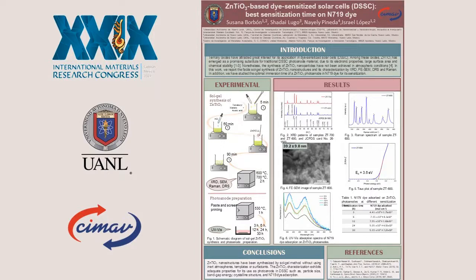In conclusion, we have synthesized monocrystalline nanostructures of zinc titanate with suitable optoelectronic properties for its application as photoanode in the DSSC. In addition, we have demonstrated that the optimal sensitization time for N719 dye is 24 hours, endowing a dye loading in the order of 10^-5 mol per centimeter.